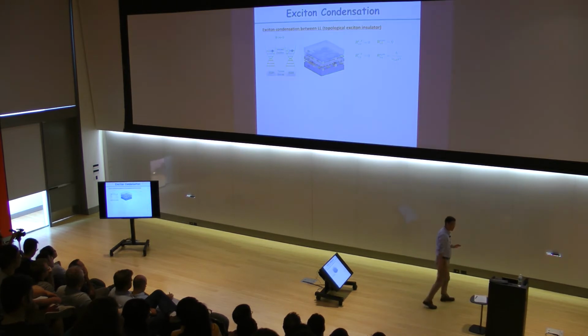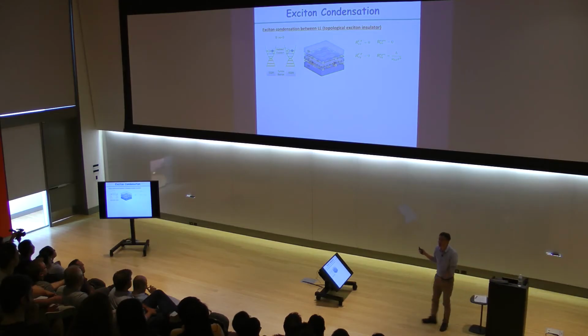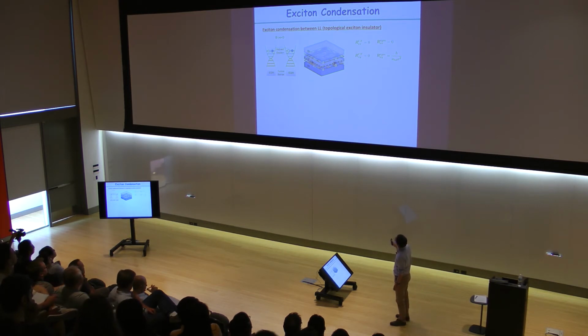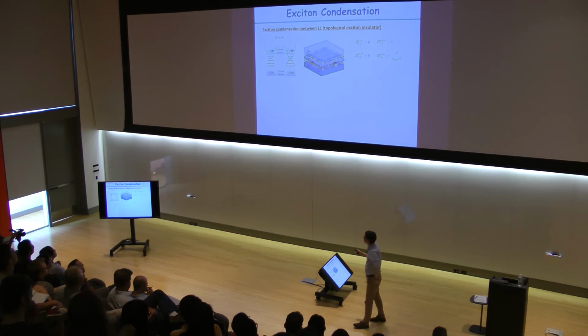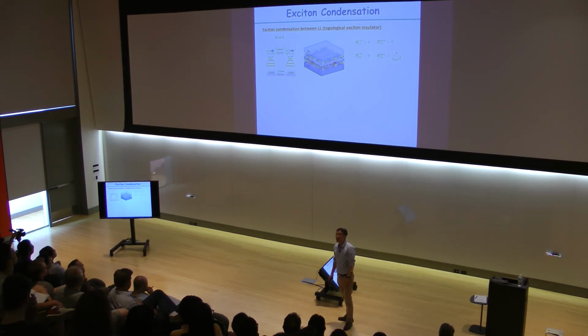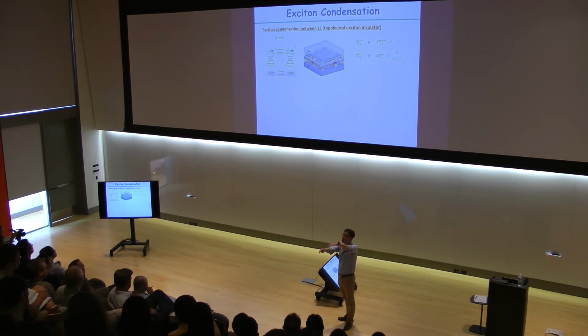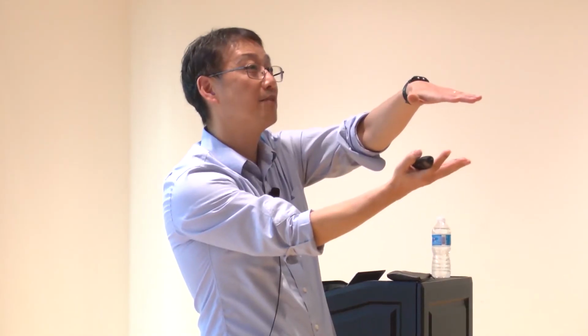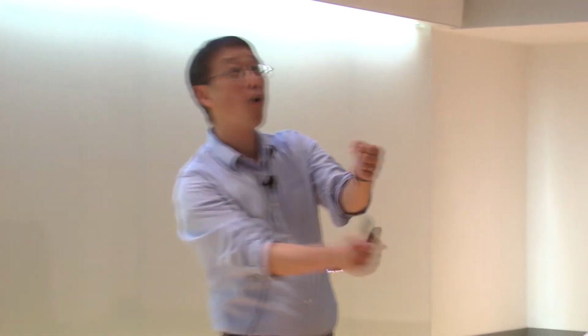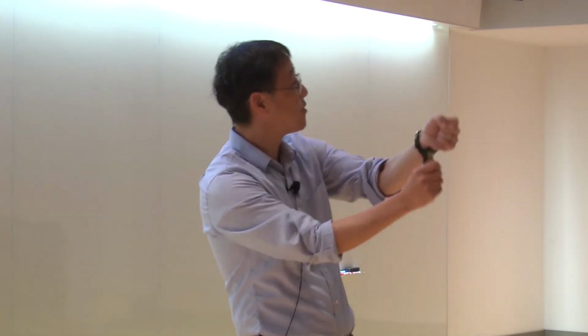But perhaps the very different thing that we cannot see in gallium arsenide, but clearly see in this particular system, is the following case. I told you that the magneto-exciton condensation is very close to the exciton condensation, except that as a whole layer, it is still a quantum Hall effect, such that the edge states do exist, right? But in principle, rather than this coupling between an electron Landau level and another electron Landau level in a different layer, what if I use the gate to turn the bottom layer of the graphene into the hole system, right? So I have the electron Landau level and the hole Landau level and ask the same thing. Now in this particular case, it is a real hole and a real electron, and still this is a real exciton forming, right?